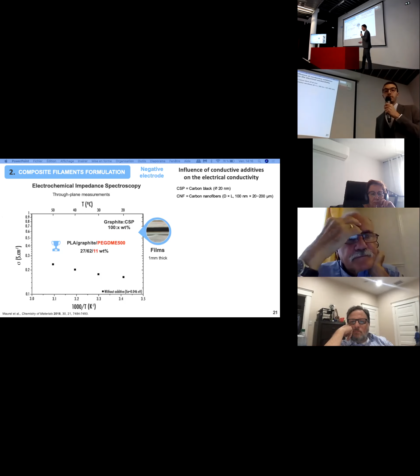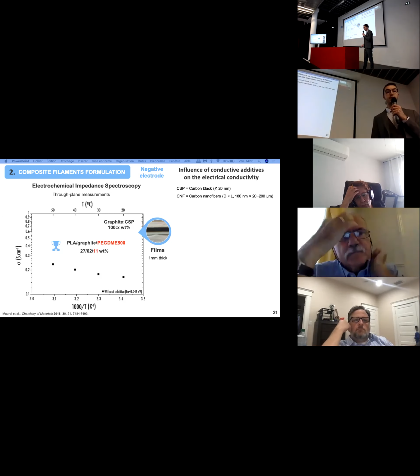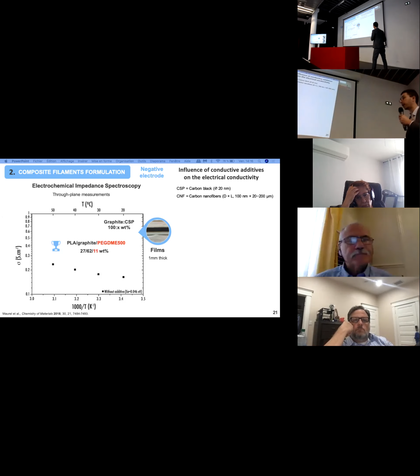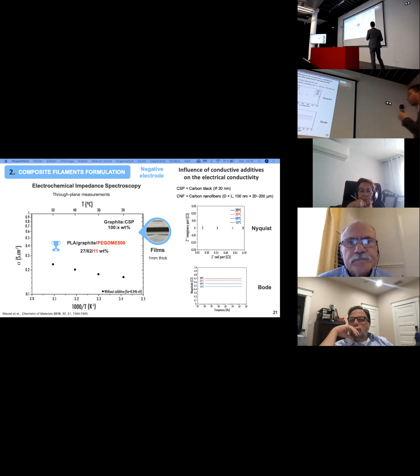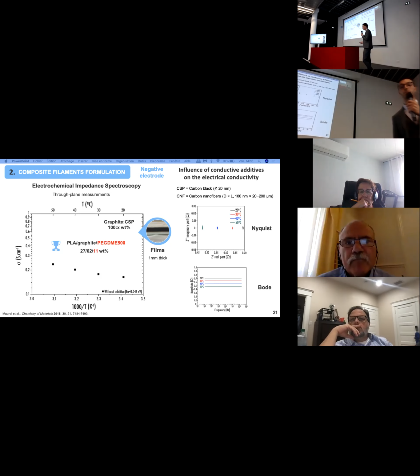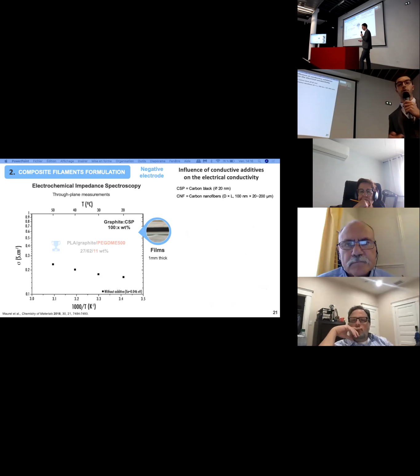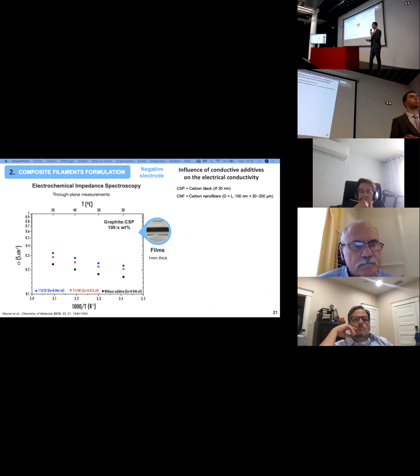So from this optimized composition about the plasticizer, we then pursued our optimization and we tried to implement some conductive additives such as carbon black or carbon nanofiber in order to improve the electrical conductivity here. Of course, as it is a purely electronic conductor, we only had classical Nyquist and Bode plots corresponding to a purely electronic conductor here, normal. So simple dots within the Nyquist plot and only horizontal lines in the Bode plot. And then we pursued our optimization. So we tried to add some carbon nanofiber, we tried to add some carbon black, and finally we reached our optimized value, which actually matches the optimization that we have done thanks to the electrochemical characterization I will discuss later.